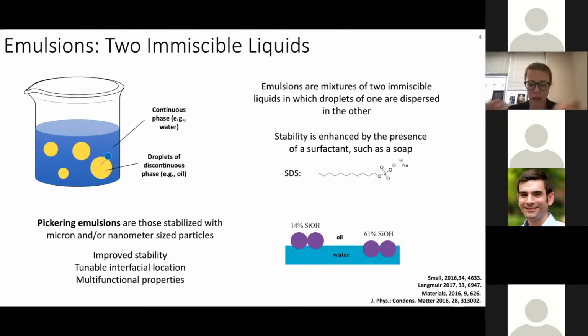But you can alkylate those silanol groups and change the wettability of the particles. It's an even distribution of functionalization on the particles. Depending on what percentage of the silanol groups you functionalize, you can get particles from the same feedstock that are either residing more in the oil or more in the water. We envision these particle surfactants as being more controllable about their location at the interface. They can also give improved stability to the emulsions because the amount of energy it takes to remove a particle from the interface is much higher than for an individual molecule.